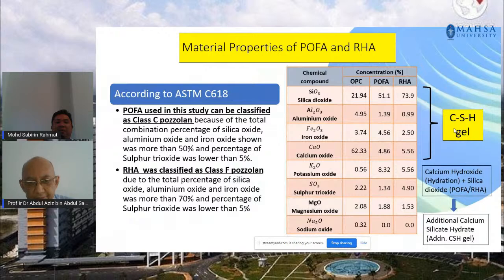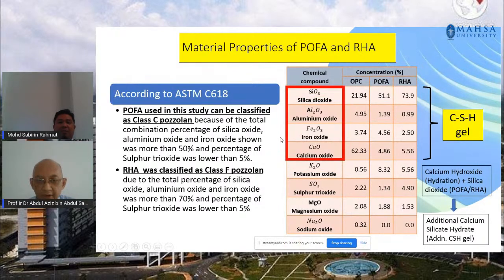Okay, as you can see from the table, we did the chemical composition for Portland cement, for palm oil fuel ash, and also for rice-husk ash. So we have 3 results, and these are the distribution of the chemical compounds in the material. As you can see there, the first four materials, silica dioxide, aluminum oxide, iron oxide, and calcium oxide, are basically the 4 top materials that you need in the cement, especially silica dioxide and calcium oxide. These 2 materials are the 2 key materials in the cement.